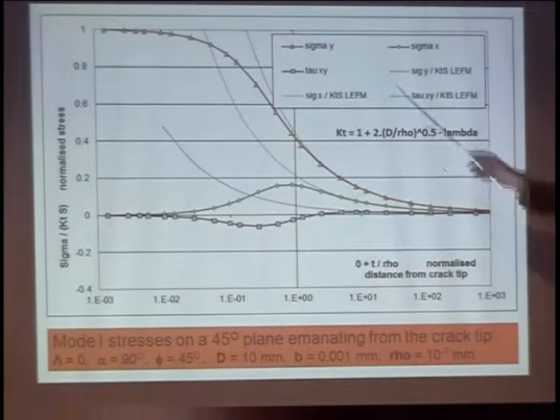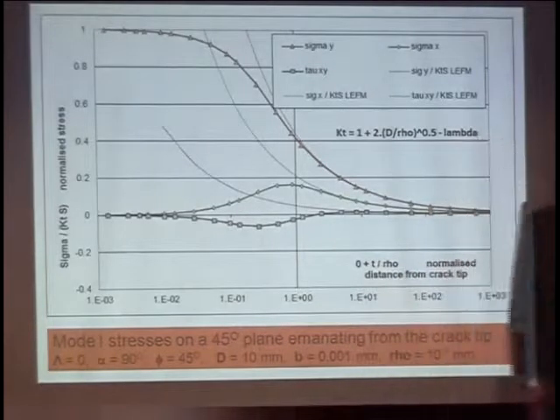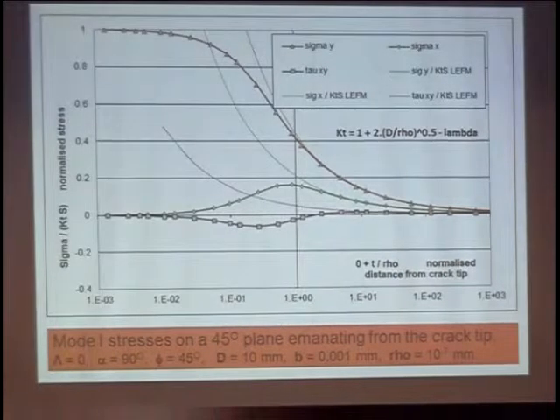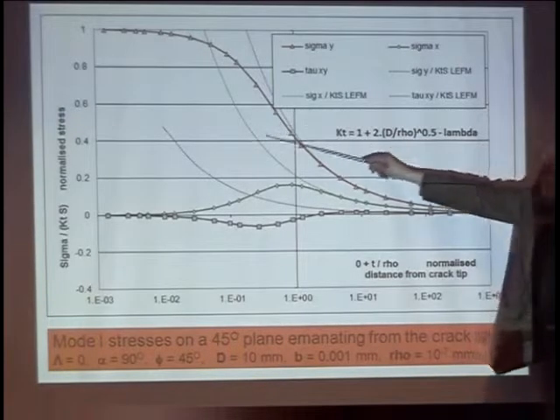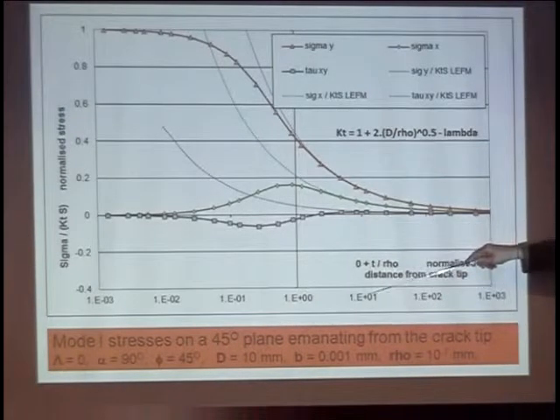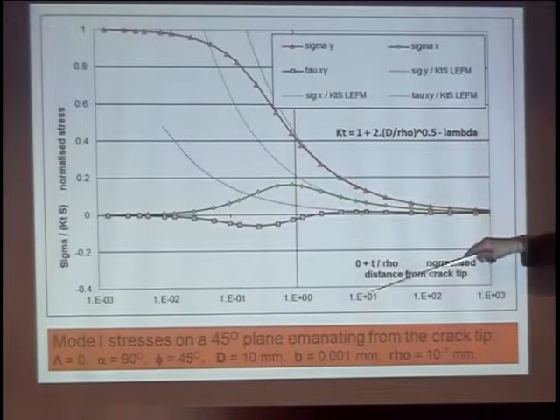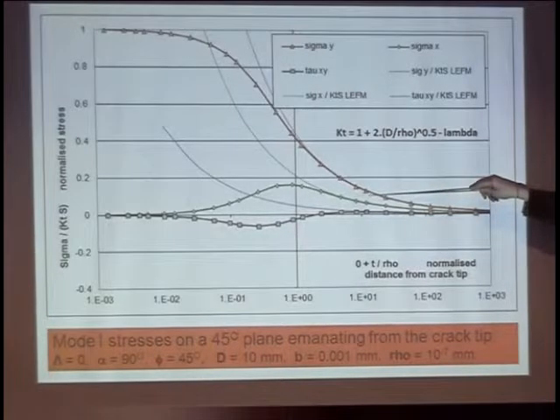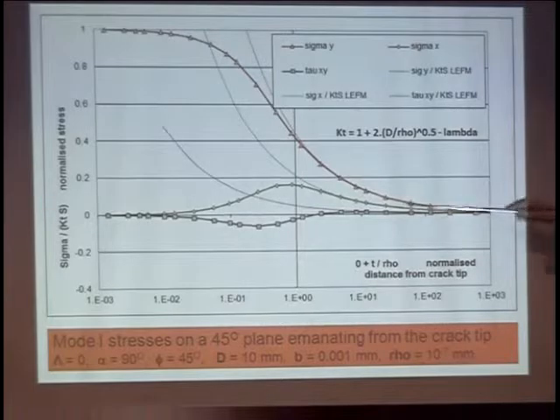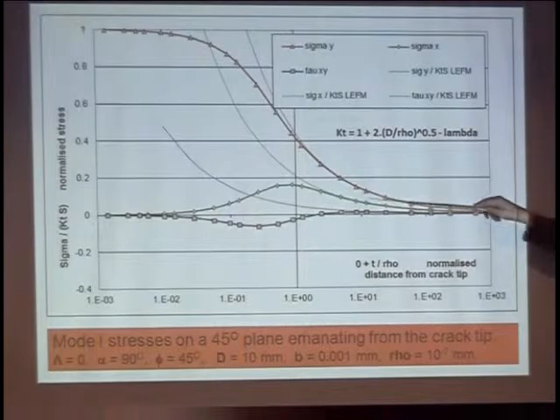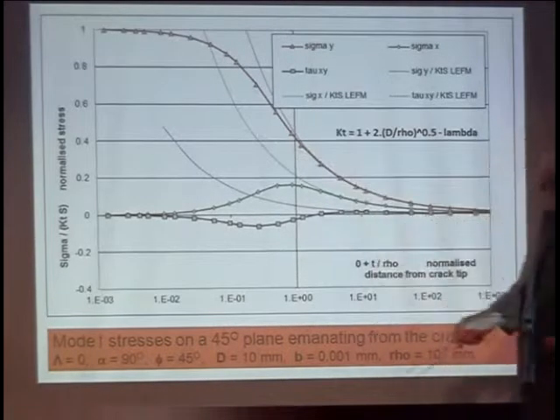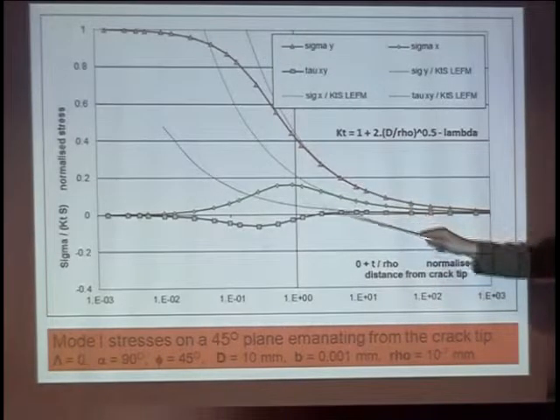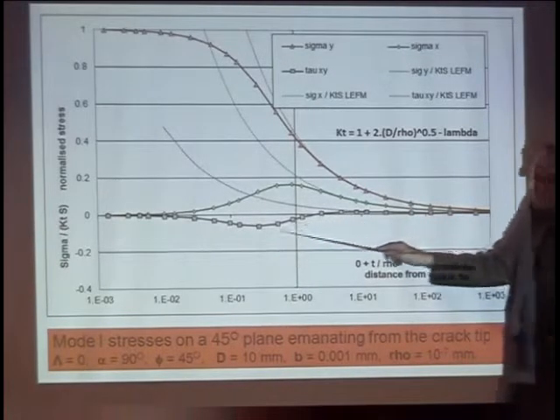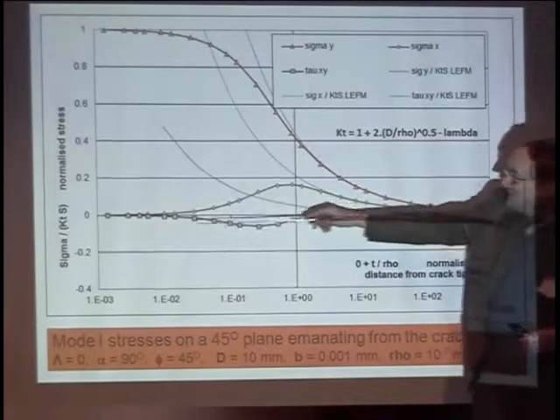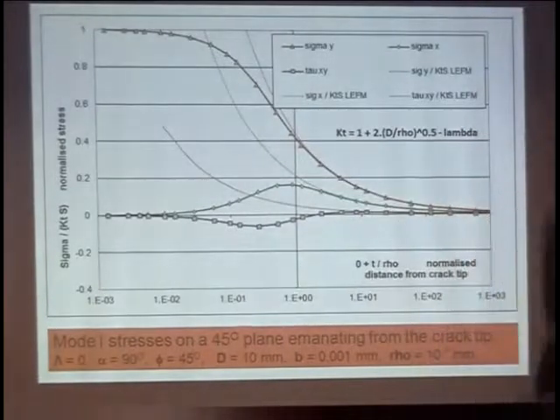This is the same thing, mode 1, but phi equals 45 degrees. So that's a bit more fun because we now see all the stresses appearing separately. The three fracture mechanics lines are there. Again, above 10 for r over rho, fracture mechanics works very well, which it should. But as we go down towards the crack tip itself, we find that we get very different results. We even find stresses changing sign, and that's why I've used a linear scale here rather than logarithmic.